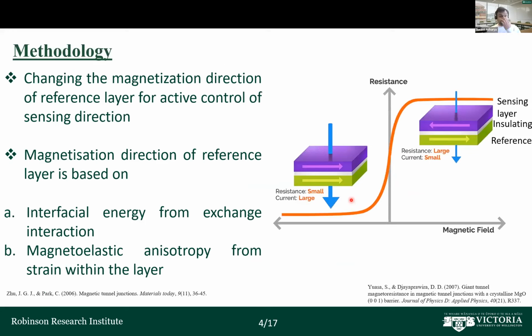For this purpose, how we are going to make the sensor is we make magnetic tunneling junctions. The magnetic tunneling junction, as you know, consists of an insulating layer that is sandwiched between two ferromagnetic layers. One of the layers is pinned, which is called the reference layer, and the other layer is free, and that is called the sensing layer. When the two ferromagnetic layers are in parallel direction, the resistance is generally low, whereas when the spin orientations are in opposite directions, the resistance is high.